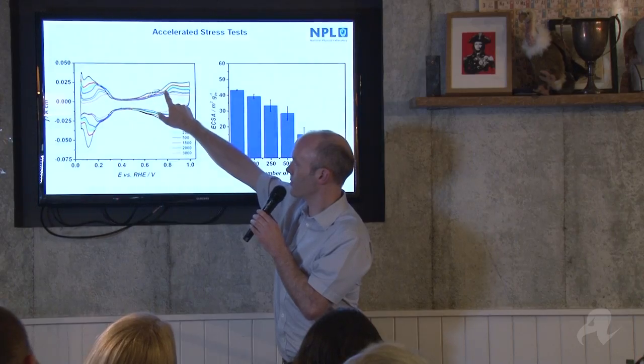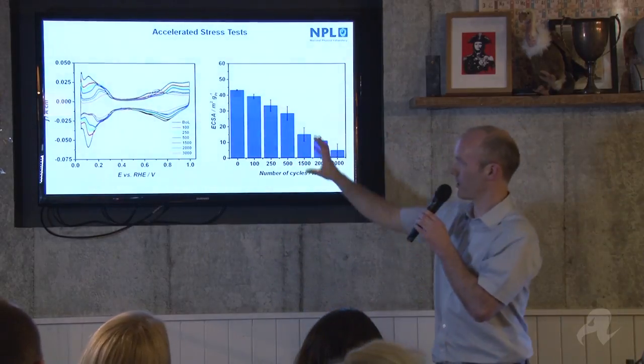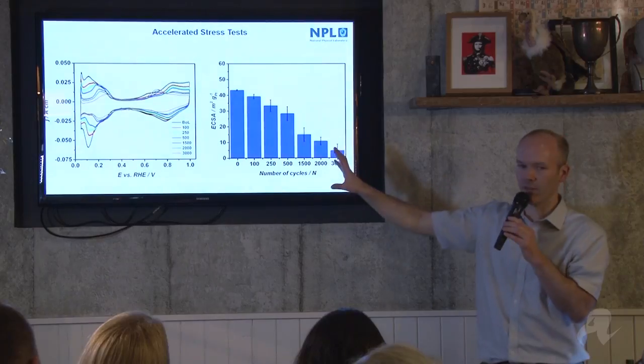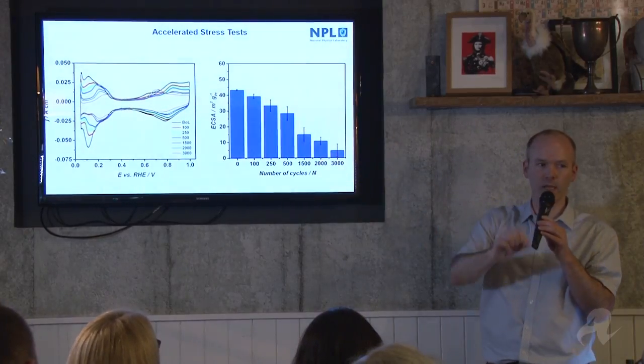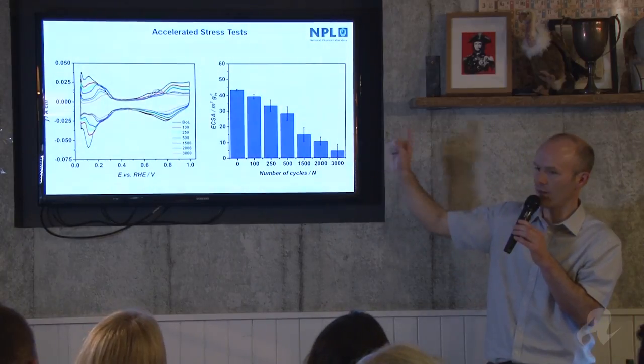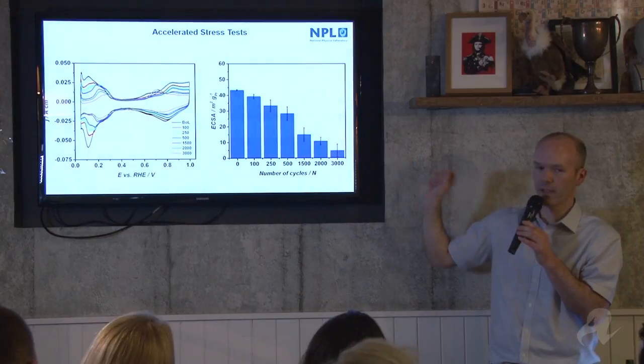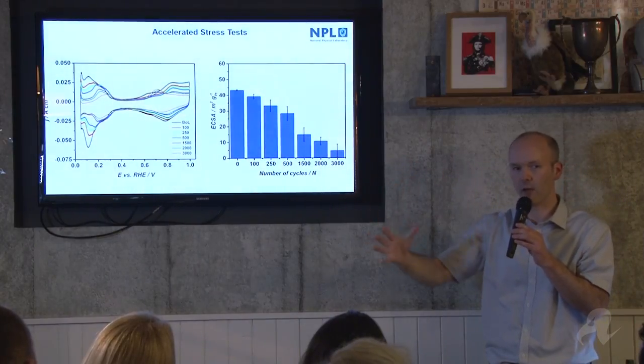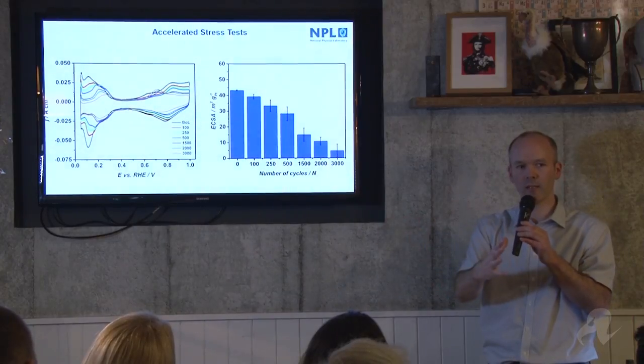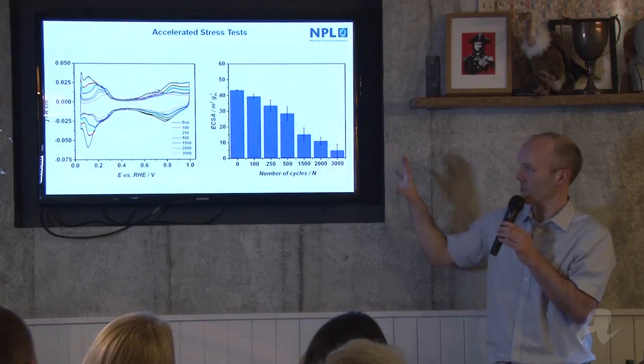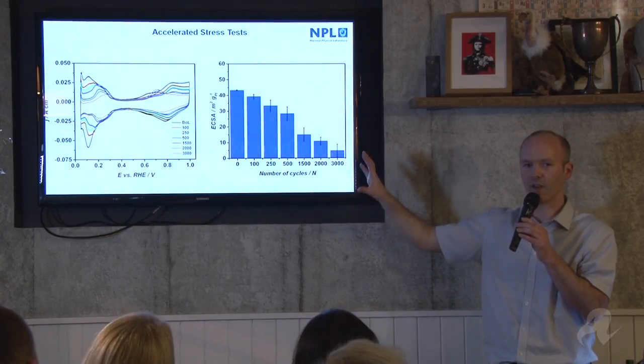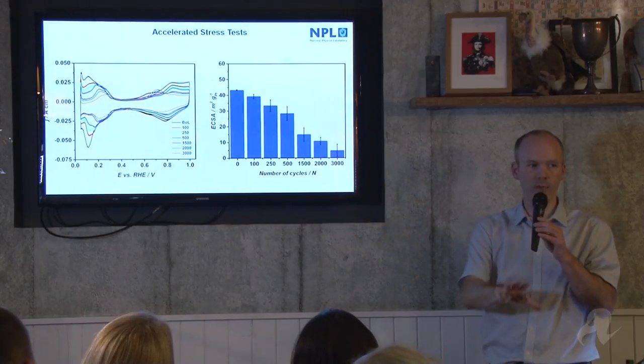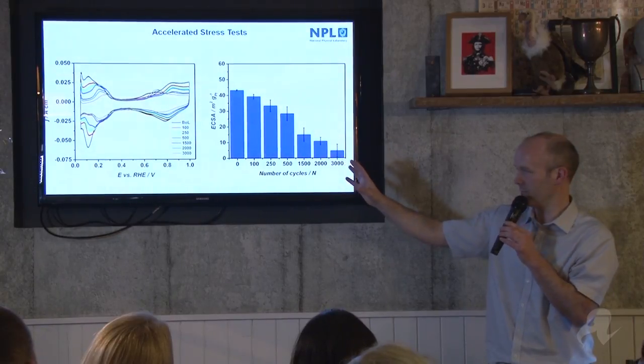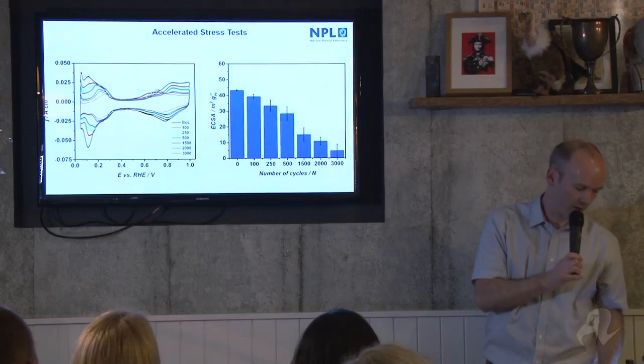But what this shows, I won't explain in detail why, we saw, as we cycled the potential of the cathode, this small peak starting to appear in what's known as a diagnostic of the surface area of the platinum cathode. And the reason we were able to do this diagnostic is because we had this reference electrode capability. And this shows very sensitively, and for the first time, that the catalyst material on the anode side is actually very slowly and in very small quantities coming across the membrane, particularly during shutdown of these cells. So this technique will be used in a very sensitive way to identify not just better cathode materials, but more stable anode materials that won't show this type of degradation. So again, we're working very closely with the electrolyzer manufacturers on this.